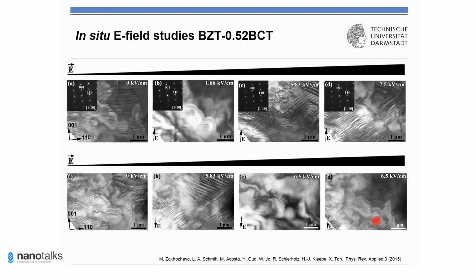So why does the transformation to a multiple domain state occur again at higher fields? Basically, we attribute it to the very high strain between neighbor grains. What I mean is that under high poling fields, each grain represents a single domain, like here, for example. With respect to this electric field, the preferred alignment of the polarization vector cannot be completely achieved within this grain and all neighbor grains in polycrystalline samples. And therefore, strain incompatibility between these grains and their surroundings plays a very crucial and important role, and that's why we have transformation to this multiple domain state.